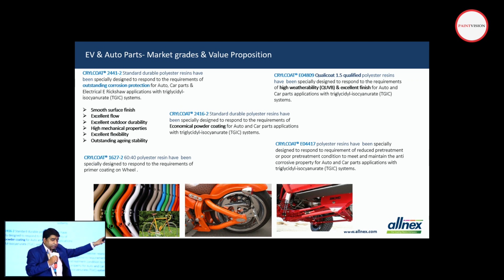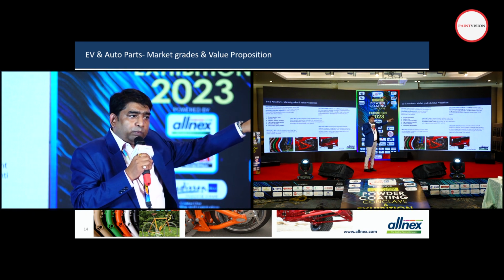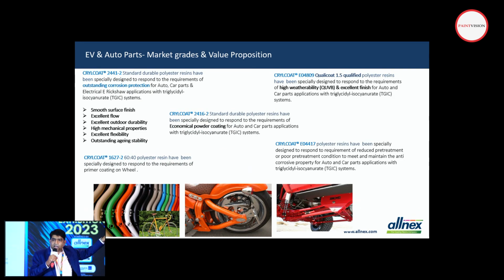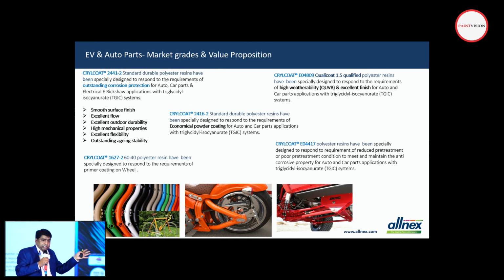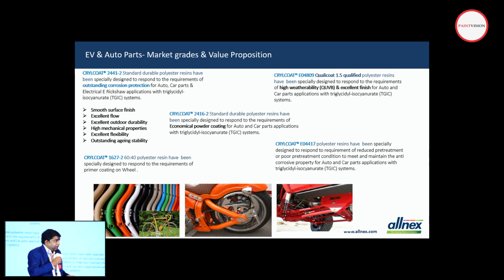These are some CRYLCOAT 2441-2. This is a standard grade. Then we also have for this market segment CRYLCOAT E04809. That is a Qualicoat 1.5 qualified grade, which means it has higher, outstanding weatherability with excellent flow. So on auto parts or EV parts, we can go with this grade, where we get a very good finish and outstanding weatherability as compared to standard grades. This is not a super durable grade, but it is better than the standard grade.